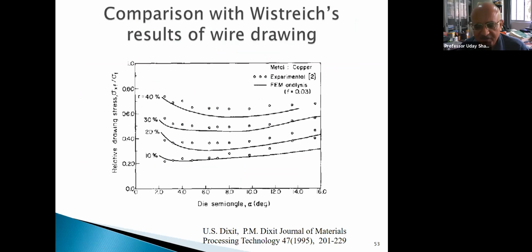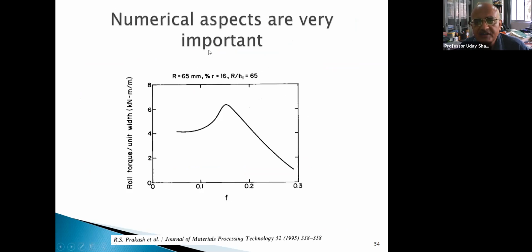Suppose we did wire drawing and we compared with experimental results. Sometimes if you do not take care of numerical results, then you may get very strange results. See, this is some result by my colleague, in some paper. Here the roll torque has been plotted with respect to friction. It is shown that as the friction increases, initially the torque is increasing, but after that it is decreasing, and it is almost going towards zero. The researcher concluded that maybe there should be an optimum amount of friction. But this is counterintuitive, and later on precise analysis showed that this happened due to numerical problems. So numerical aspects can be very important.